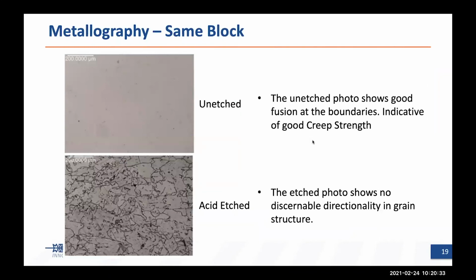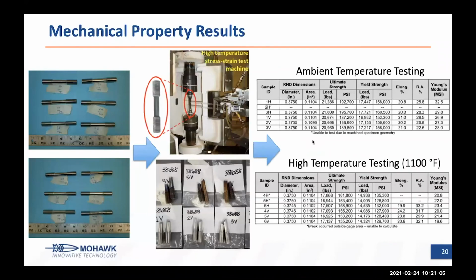The next one we wanted to take a look at: do we get good bonding internally? What is the grain? Is there orientation to the grain? In a couple of the metallographs shown here, we just took some random samples from the material. The unetched photo shows that we had good fusion at the boundaries, and we don't have voids and things of that nature, so it's indicative of good creep strength. The acid etched component says there's no real directionality in the grain. That gave us additional confidence that the material is going to be what we want and what we need.